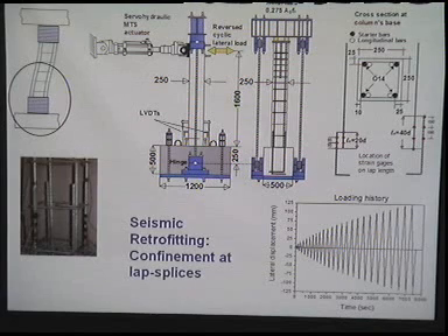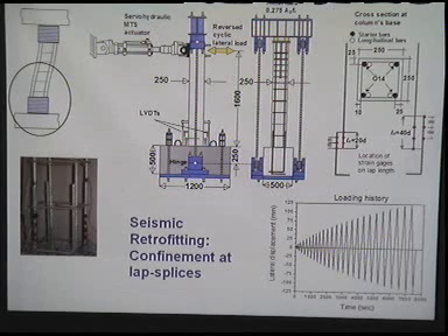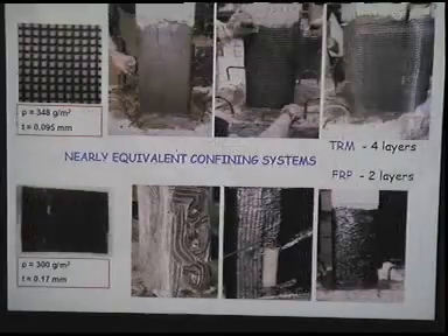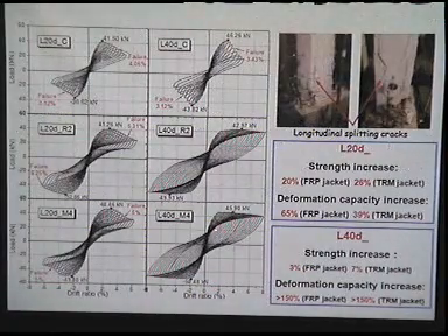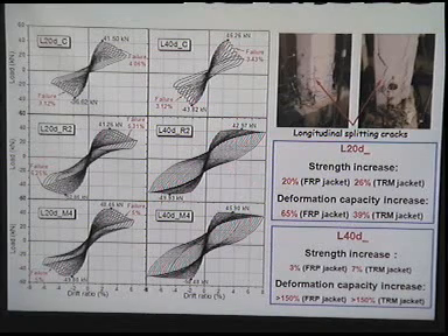I will skip that. We did similar tests to prove that those materials can also provide very good confinement at the base of columns when we have lap splices, which is quite typical when we have short lap splices, which is quite typical in old reinforced concrete frames. Our conclusions in that case are exactly the same, that both TRM systems and FRP systems are practically equivalent. They provide the same level of confinement at those lap-spliced areas.